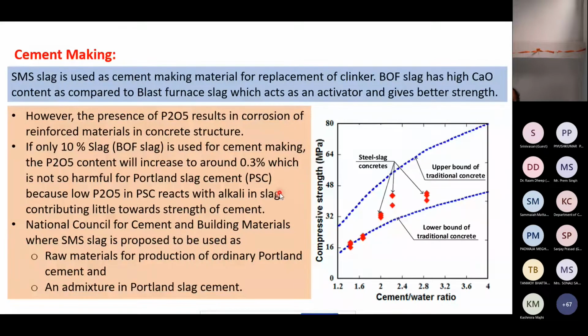Even this slag, civil engineers tried to utilize it for cement making because it contains the calcium, it contains the silica, it contains the iron. So if by proper modification it can be utilized for making the cement, then it is going to be the better utilization point. So this slag is used as a cement making material for replacement of the clinker.